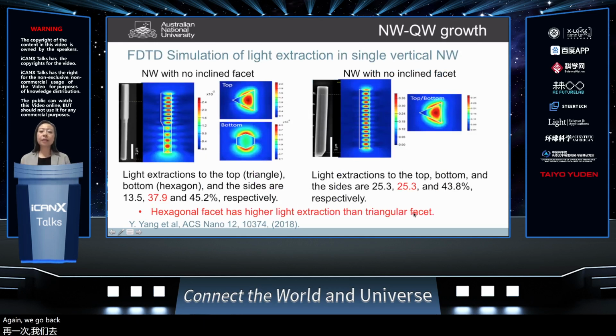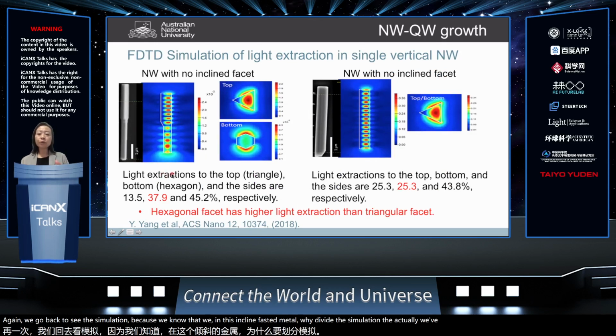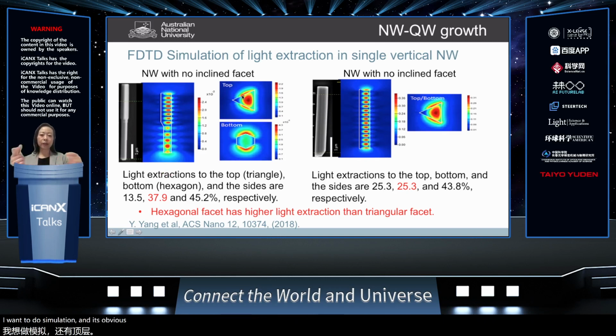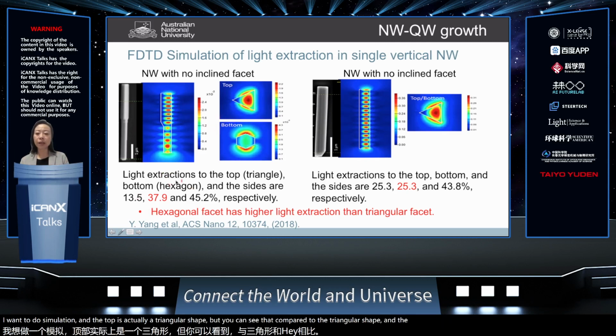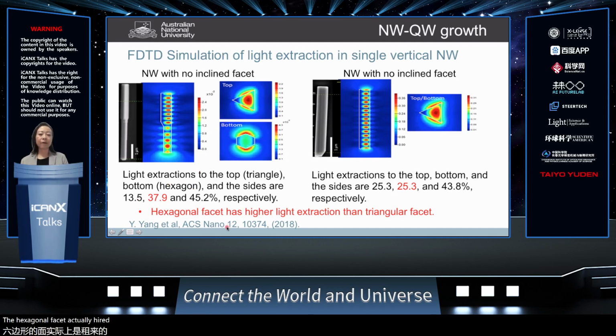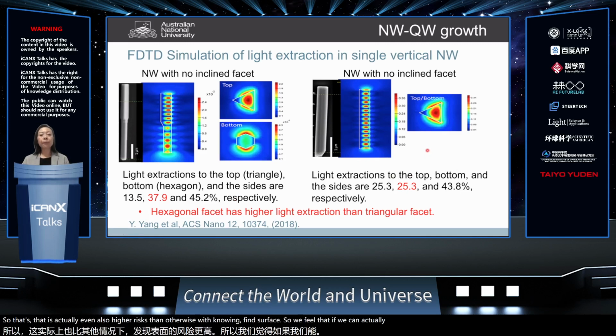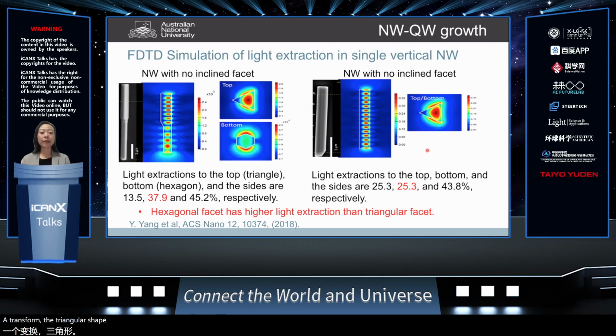Again, we go back to the simulation, because we know that in this inclined facet nanowire device, actually we use the Wurtzite base, which is hexagonal shape, to do the simulation, and the top is actually triangular shape. But you can see that, compared to the triangular shape, the hexagonal facet actually has a higher light extraction efficiency than the triangular facet. That is actually even higher than for the nanowires with no inclined surface. So we feel that if we can transform the triangular shape into hexagonal shape, we may be able to further enhance light extraction, right?